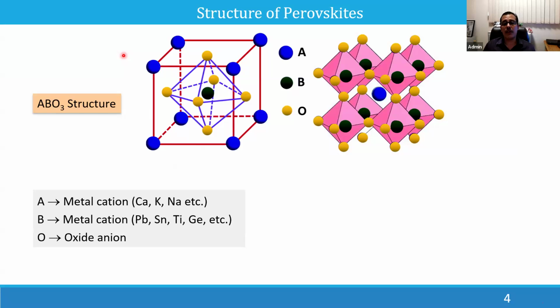So to get a better understanding of the material, we will first try to understand its structure. Basically, it has a very simple structure called the ABO3 structure. In this ABO3 structure, both A and B are metal cations. Normally, A is a monovalent cation like cesium plus, potassium plus, or sodium plus, and B is normally a dication or trication, mostly lead or tin or titanium, germanium, bismuth, etc. And O is the oxide anion. So these three components are there: A cation, B cation, and oxide anion. And the B cation is actually surrounded by 6 oxide anions, forming an octahedral structure. So that is the basic structure of a perovskite material.